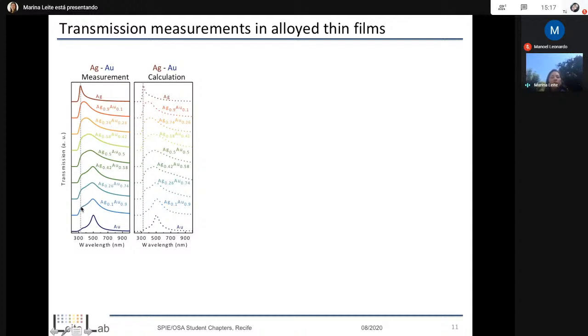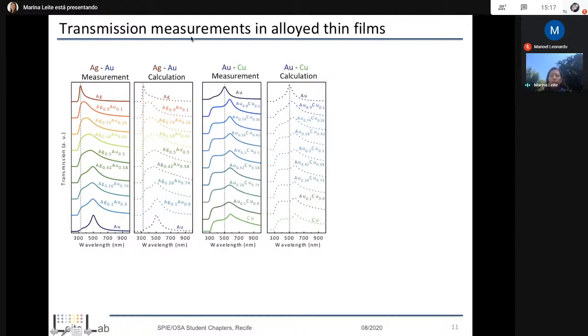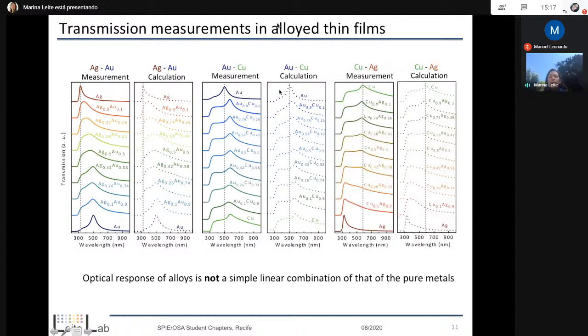Even once we add a tiny bit of silver, we already have the contribution. This shoulder, as I'm pointing here, I'm assuming you can see my mouse. And then things got a little different. Around 50-50% of each metal, we basically have one broad peak, and eventually we essentially have only the silver contribution, as we should. Our measurements were in very good agreement with our calculations. A lot of data, but just to give you an idea, we did definitely have a similar, very good agreement for the other two binary mixtures.